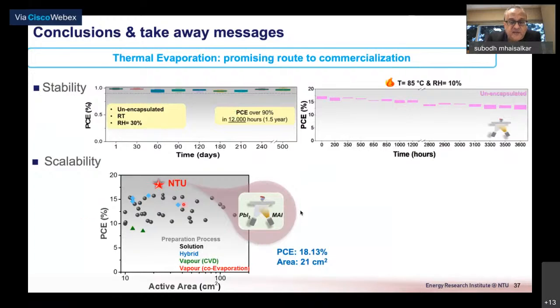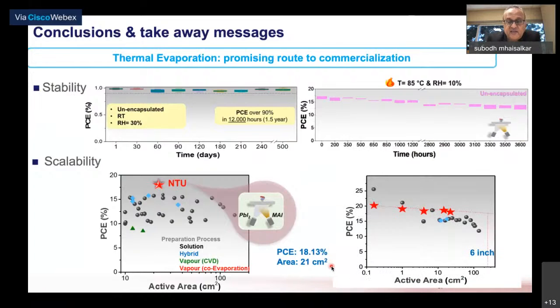From a scalability perspective, we have shown PCEs of more than 18% on 21 centimeter square devices, and this probably is one of the highest in terms of size compared to all the other solution processed, hybrid, or CVD, PVD processes as well. What I'm also showing on the right-hand side is what we can estimate the performance of these devices to be when we scale to 6-inch.